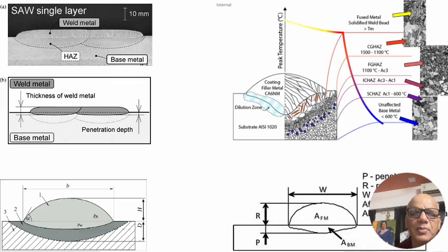That's the technique which is different from the normal butt joint or a fillet joint, and that's why special slides have been prepared here. The configuration of the weld profile is very important, and that is where this angle comes into play, because our second pass is going to be either on this side or on this side, which we will see in the next slide, and that must get properly fused with this entire line here, as you can see from the overlap which has been given. If the weld bead penetration pattern is so deep, then the dilution is going to be very high, because this is going to be the diluted material, and we want the bare minimum dilution from the parent metal to come.